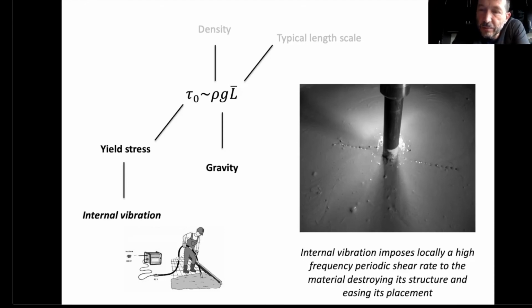Internal vibration, the insertion of this vibrating poker inside the material, imposes locally a high frequency periodic shear rate, and it destroys the structure of the material, destroys this network of interactions at the level of the cement grains, and the yield stress turns to zero for a short time and eases the placement of the material, with of course the potential risk of instabilities of the material if you vibrate it too long.